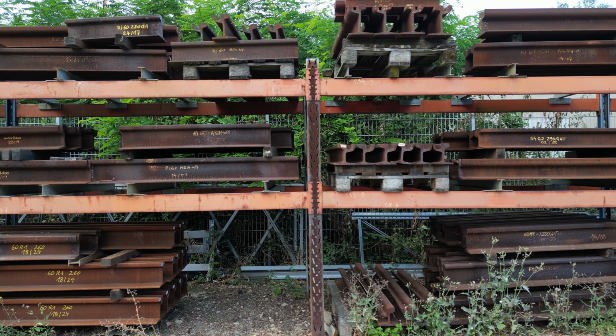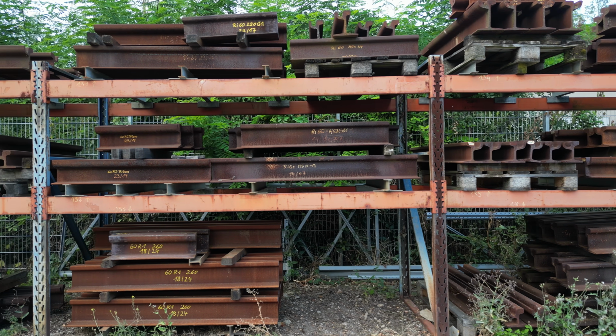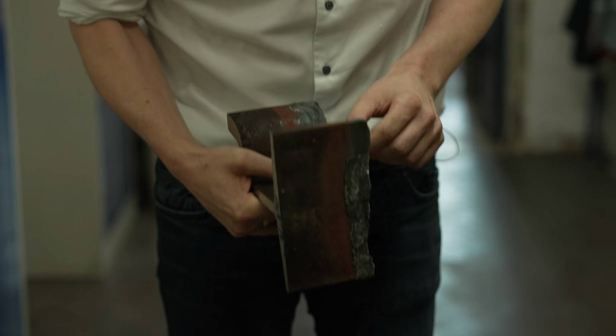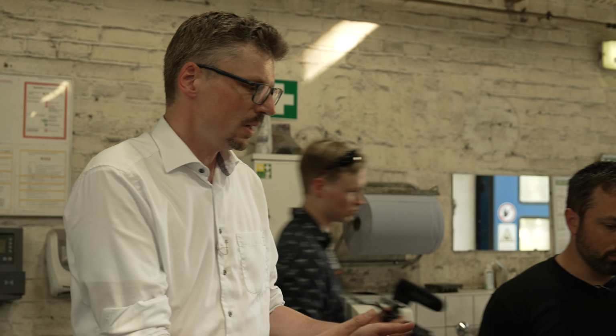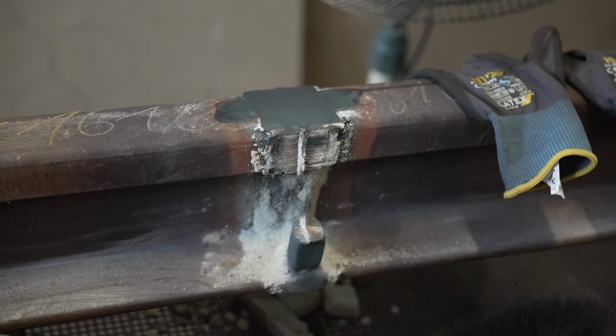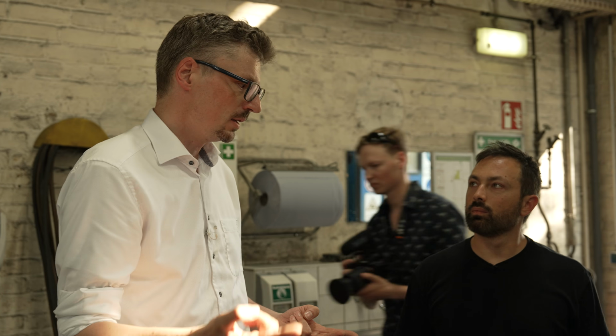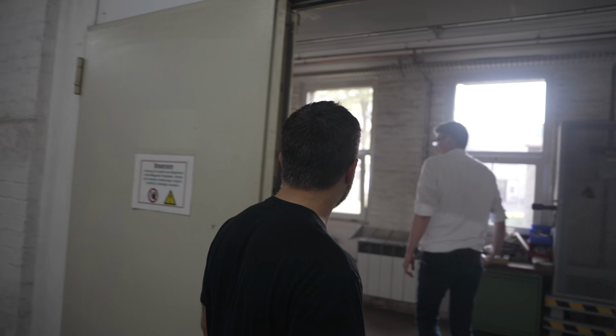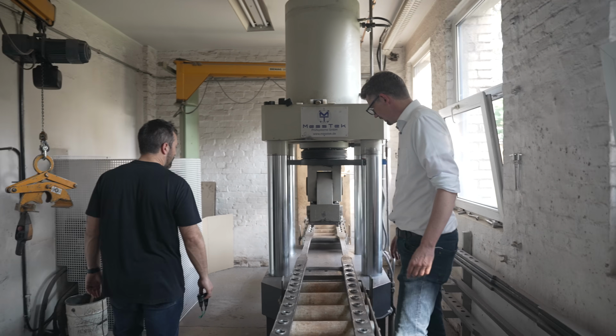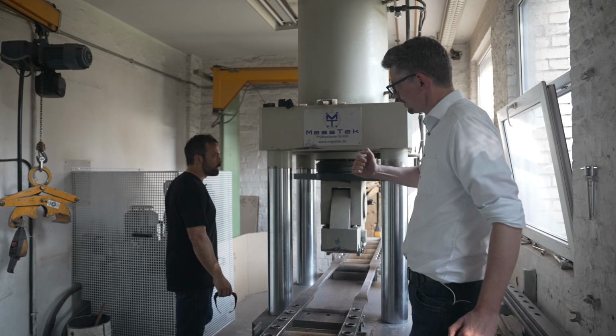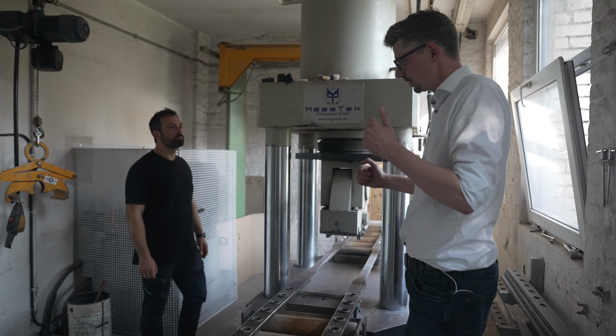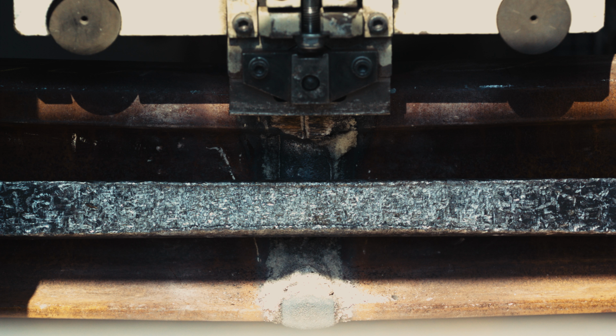Well, at Goldschmidt, they actually take sections of rail that they have welded and they test them until failure. Every 200, basically, we create one test weld, and we analyze it in terms of chemistry, we analyze it in terms of hardness, and we analyze the bending. And this is the bending press. They put this in, right? And then the force comes from top and then goes down and it breaks it. And we measure the speed and also the force.